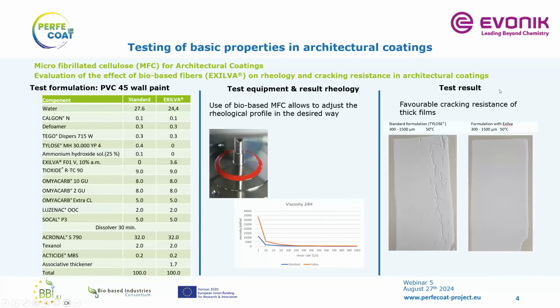And what we looked at in terms of performance in the final coating, we applied both coatings next to each other using a bar which is graduated in terms of thickness, from 300 micron to a very high thickness up to 1500 micron. And you can see on the standard on the left side some cracking, which occurs when the thickness is increased. And with Exilva, we had a very smooth and nice appearance throughout the range of thickness, which indicates an improved robustness of the paint, which brings advantage in case paint is applied a bit thicker on the corner or if there is some sagging, so it's still looking good after all.